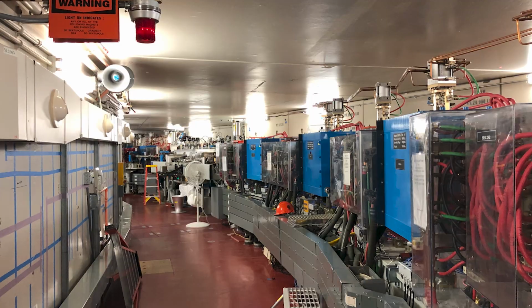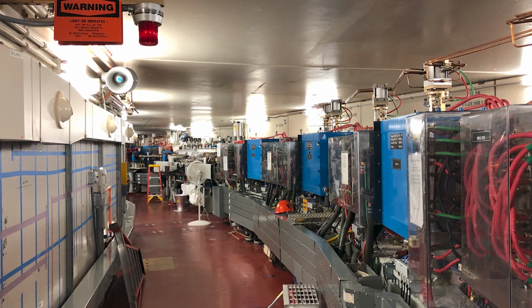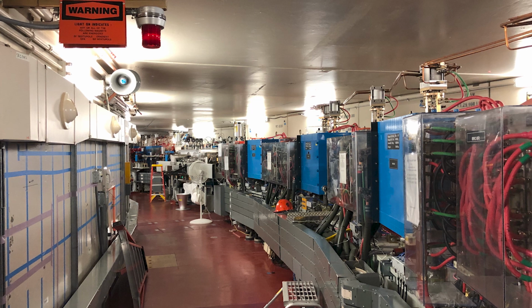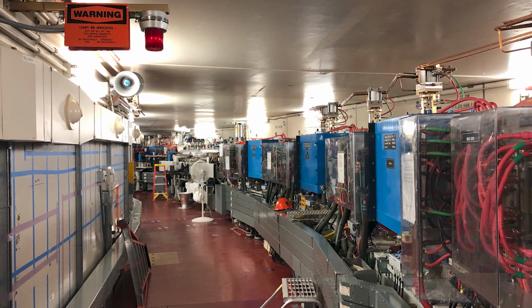These facilities, or synchrotrons, have enormous tubes, often more than 100 meters long, where electrons travel in circles. The acceleration creates photons with high energies. We use these high-energy photons, or X-rays, to probe excitations in the measured materials. Let me show you an example. You can see here a 3D magnetic image of a permanent magnet, neodymium iron boron. Here we use a special 3D magnetic imaging technique to decipher the structure in all spatial directions.